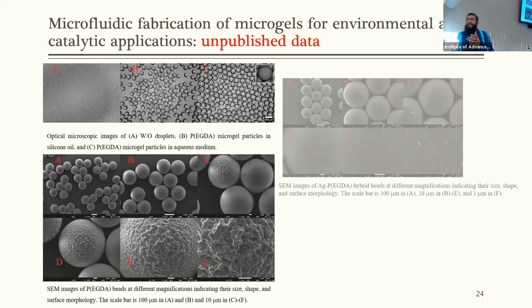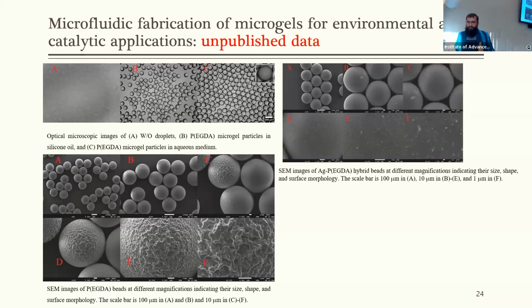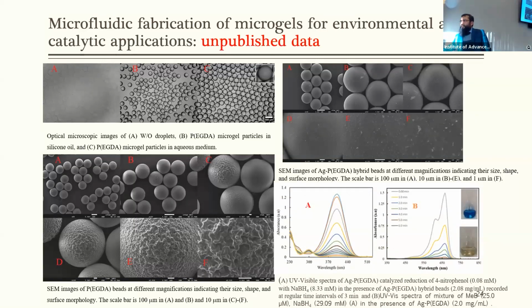These microgel particles can be easily recovered from the aqueous medium by simple centrifugation or filtration, or we can recover them by a simple sedimentation method, because these particles have a large size and can easily settle down after extracting the metal ions from aqueous medium. Moreover, we were successful in fabricating silver nanoparticles in the outer region of the microgel particle, and we use this hybrid system as a catalyst for degradation of 4-nitrophenol and methylene blue present in aqueous medium.